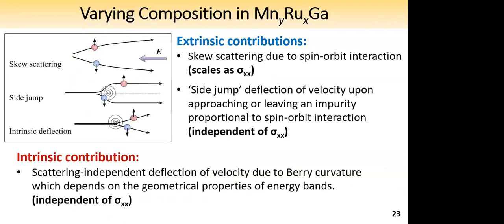And this is what I'm showing here. So first we have the extrinsic contributions. That includes skew scattering, which is due to spin-orbit interaction, and it scales as sigma xx, which is the longitudinal conductivity. We have another one, which is called side jump, and it's deflection of velocity upon approaching or leaving an impurity, and is also proportional to spin-orbit interaction. And in this case, it is independent of sigma xx.